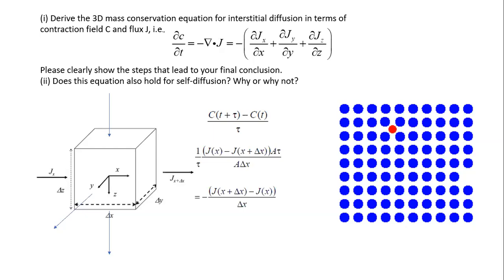Yeah. So the whole point is just to give you some idea, and motivate you to work out under what conditions you can apply this equation to study self-diffusion. So if you're working with an alloy with a lot of interstitials, but also self-diffusion, you know that you have to use this with caution, right? Because the vacancies might not be conserved, so the equations may not be right for self-diffusion. Does that make sense to you? So that's the whole point.